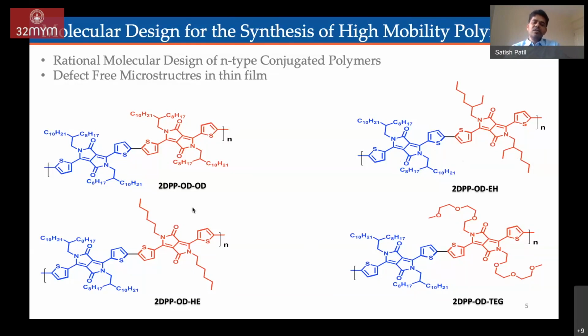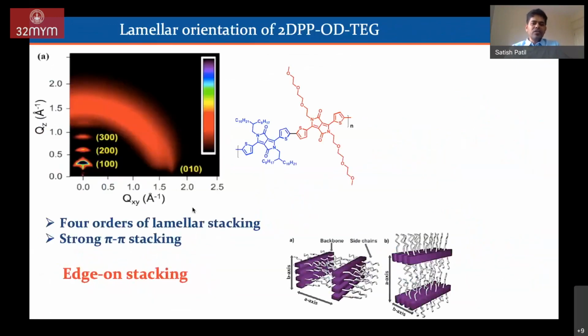When we started this research, for example, Buckminster fullerene was a good n-type, but it again has a very low charge carrier mobility. So we wanted to address this question: can you make a pi conjugated polymer with controlled, defect-free microstructures in thin film with very high mobility? So to our surprise, when we took this polymer and cast a film, we indeed found, in this grazing incidence scattering measurement, 3 to 4 orders of lamellar packing.